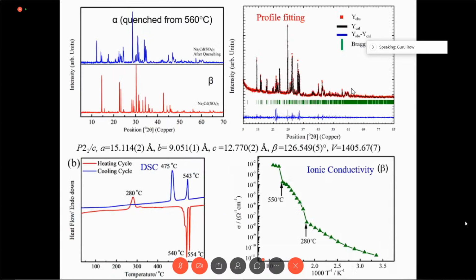And this can be established by a series of studies using powder diffraction. The technique called profile fitting will establish the structure. And what is more interesting is the behavior of ionic conductivity. As we heat the system, at 280 degrees centigrade it suddenly changes to a higher conductivity. And at around 550 degrees, we see that it goes towards superionic conduction.